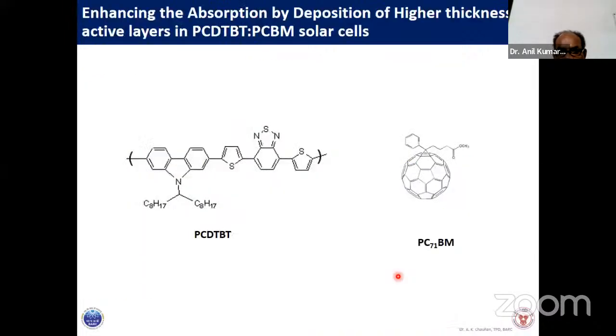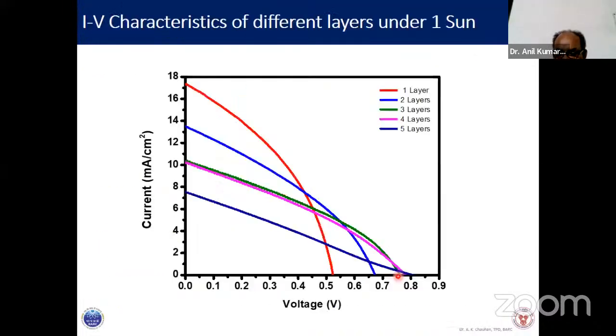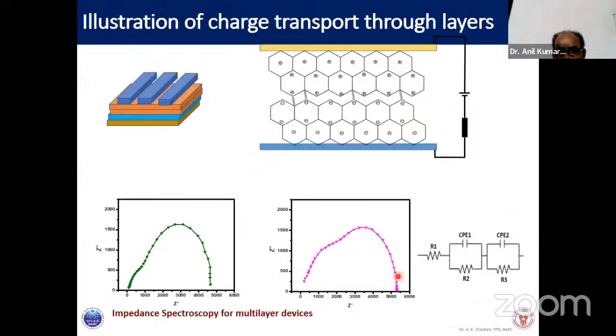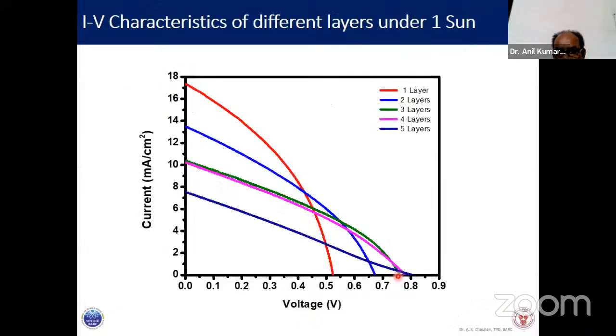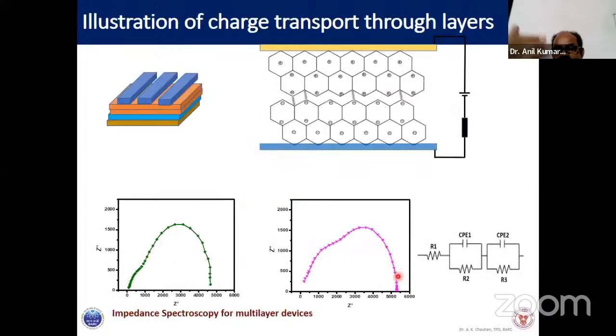Another thing which we did was deposit layers one by one, one layer over the other, several 5-6 layers, to increase the absorption. But this created another problem of charge trapping, because you have different layers that are imperfectly added to each other. So there is a source of charge trapping in between. This is understood by impedance spectroscopy.